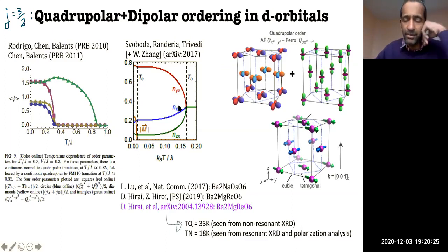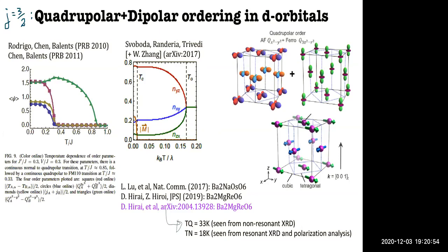that I'll talk about. But in some of these cases, if you're looking at modulated orders, then it's harder to do with Raman, because that's looking at a zero momentum transfer. It's looking at kind of uniform orders, as opposed to staggered orders, where there is some layer to layer difference in the orbital order. That's harder to get with Raman alone.